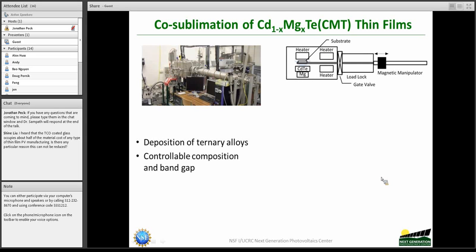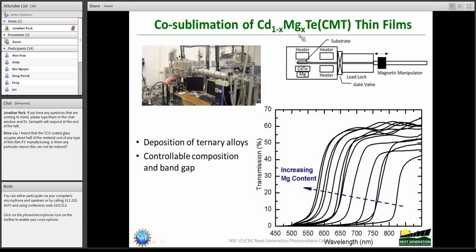Now, the higher band gap material that we have chosen is cadmium magnesium telluride, short form written as CMT. And in order to produce this material, we have developed what is called a co-sublimation process. Here we have one sublimation source sitting on top of another sublimation source with passages and valves and what have you, so that we can have different amounts of the vapor from these two coming in, and we can lay down these cadmium magnesium telluride films.